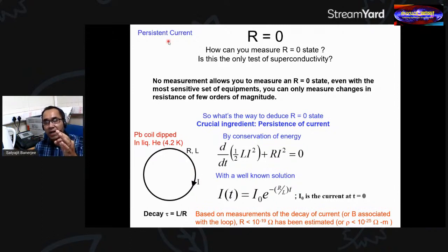So if you apply a current and switch off your power supply, you can put current into a loop of wire and then remove your power supply. You can set the current up and it will continuously circulate for an indefinite period of time, and based on these experiments they have obtained upper bounds on the resistance: the resistance in the superconducting state should be less than 10 raised to minus 19, almost zero for all practical purposes.